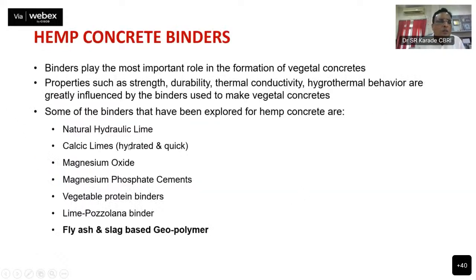Initially, binder has a very important property. It dictates the properties like strength, durability, thermal conductivity, hydrothermal behavior, and so on. So we started with natural hydraulic lime, then calcic lime, magnesium oxide, magnesium phosphate, then vegetable protein binders, lime pozzolana. But the best properties we have found with fly ash and slag based geopolymer, where we are getting the maximum strength. So our focus is more on this binder, although we have made the composites with these binders also.